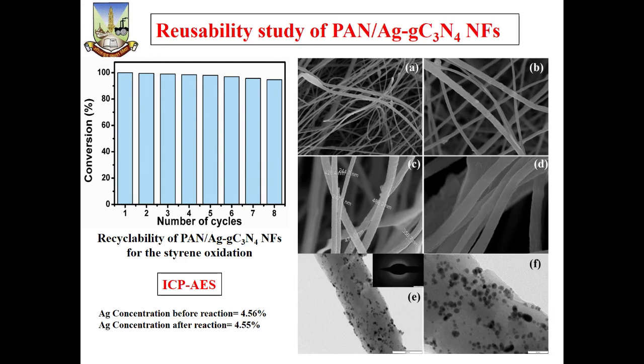This is the reusability study of PAN Ag-gC3N4. We have done the study up to the 8th cycle. We found that from the first cycle to the 8th cycle, there is a marginal decrease in the percent yield of the final product. But there is no loss of the catalytic activity of that heterogeneous catalyst. The catalyst activity remains the same. The structure of that particular catalyst remains the same.